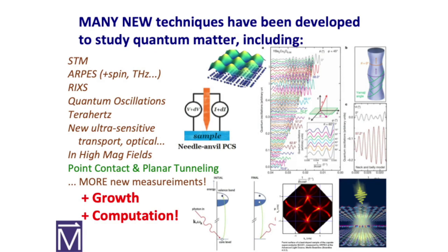You put one of these materials in a high field at the magnet lab, or other magnet labs, and you measure the Shubnikov-de Haas oscillations as a function of angle, and you can actually map out the Fermi surface. You can see that in the cuprates you have this interesting quasi-two-dimensional Fermi surface. These measurements were only possible because of the development of the techniques, the high-quality crystals, and the way computation techniques have gone forward so much.